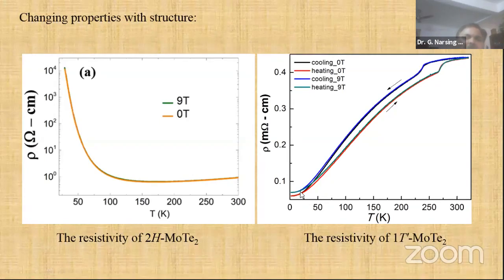So this is the 2H material. This one is 1T prime. You can see here, there is a small range around 240 to 260 where there is a structural change. Here it is semiconducting behavior. This is the 1T prime structure, and this is Td. So these are two different material structures, one is T prime, another one is Td. If you measure low temperature X-ray, you will find that type of structure. This is a phase transition with decreasing temperature. Due to the making conditions, these two phases will come, the 2H material and the 1T prime material.